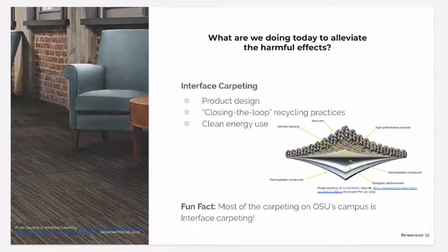For the carpet tile, the nylon is stripped of the backing and is melted down to be re-extruded as new nylon yarn. The backing is ground up into vinyl pellets and melted and reformed into new carpet backing. For the used luxury vinyl tile, it is also ground up and turned into carpet backing. Additionally, the use of tiles in carpeting and vinyl is much more sustainable because when part of it is ruined, that one tile or few tiles can be replaced rather than all of it having to be ripped up in large sheets and replaced.